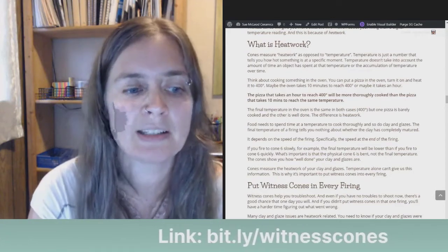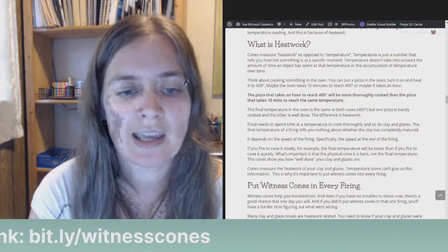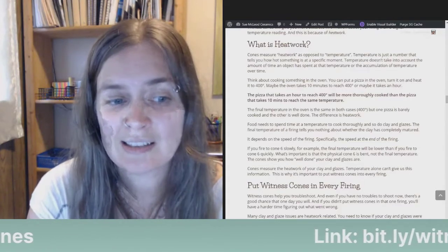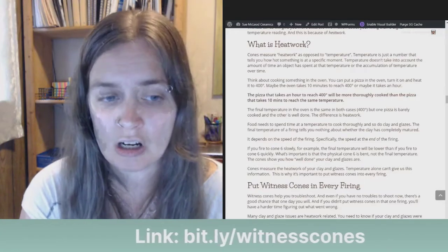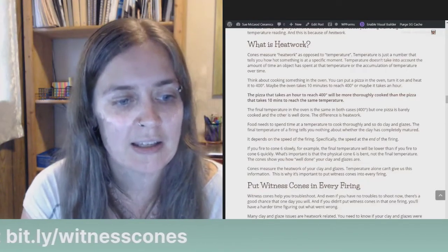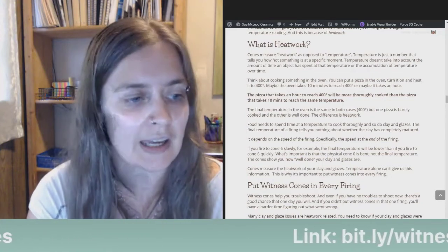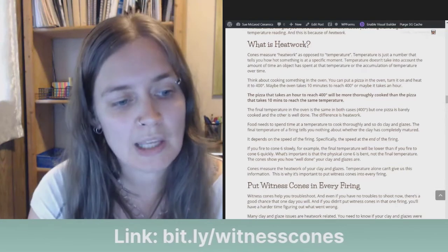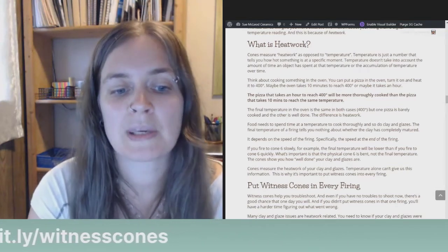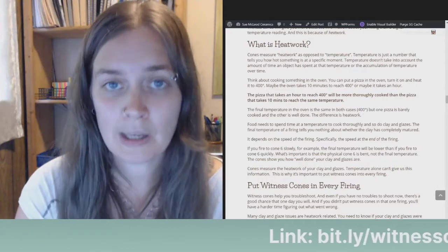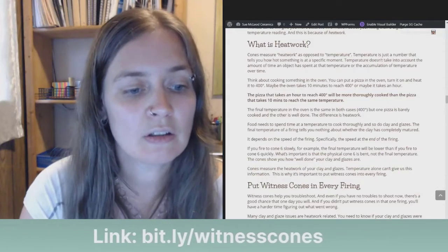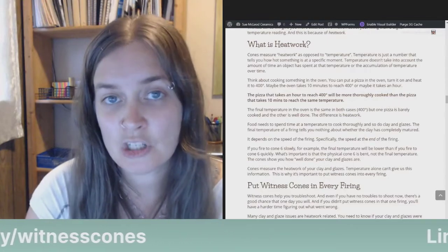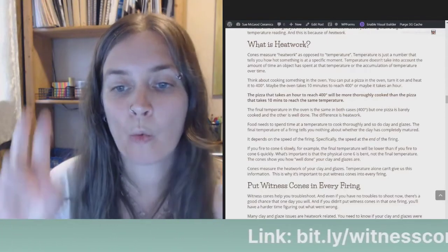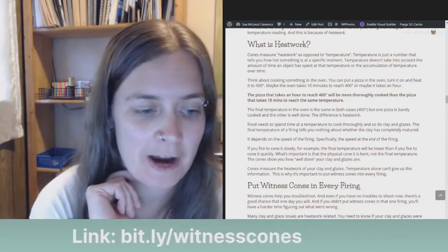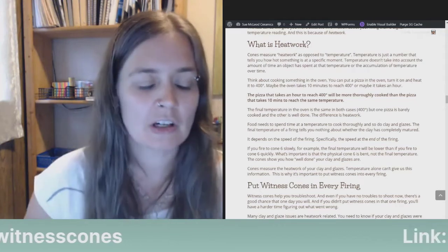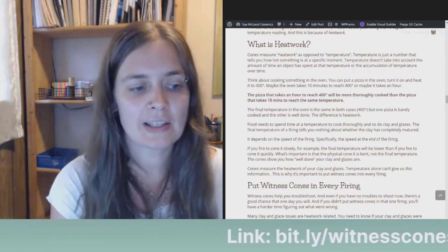Food needs to spend time at a temperature to cook thoroughly, and so do clay and glazes. The final temperature of a firing tells you nothing about whether the clay has completely matured. It depends on the speed of the firing, specifically the speed at the end of the firing. So if you fire to cone 6 slowly, for example, the final temperature will be lower than if you fire to cone 6 quickly. What's important is that the physical cone 6 is bent and not the final temperature. The cones show you how well done your clay and glazes are. Cones measure the heat work of your clay and glazes. Temperature alone can't give us this information.